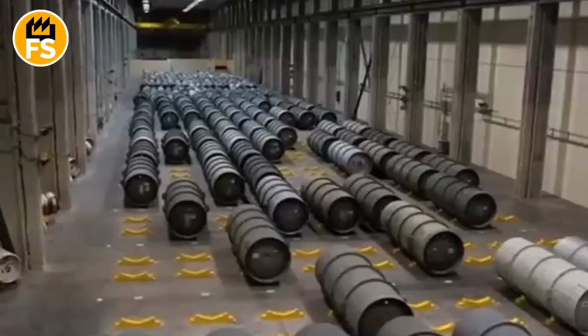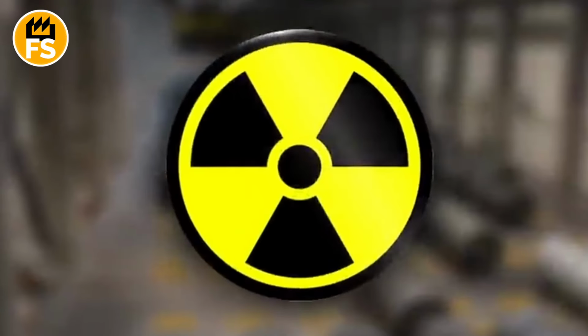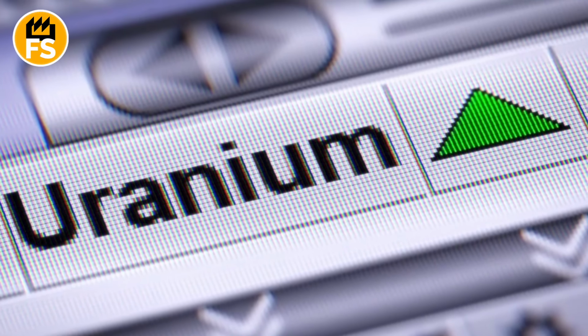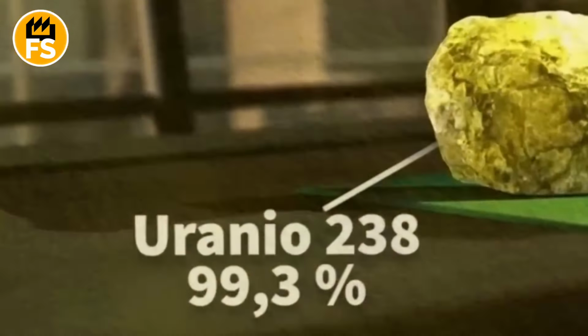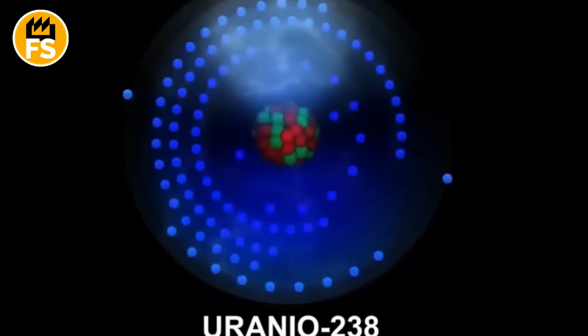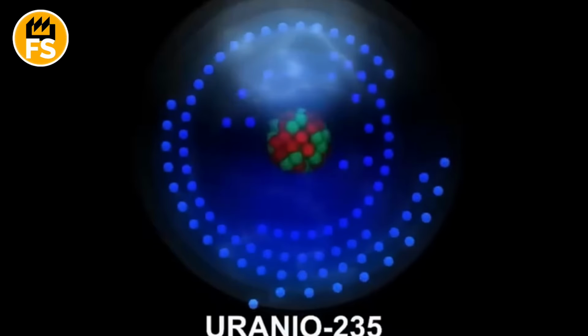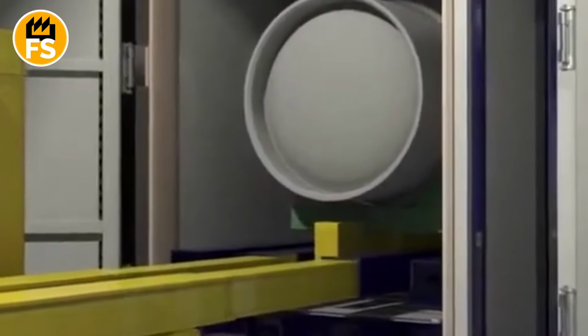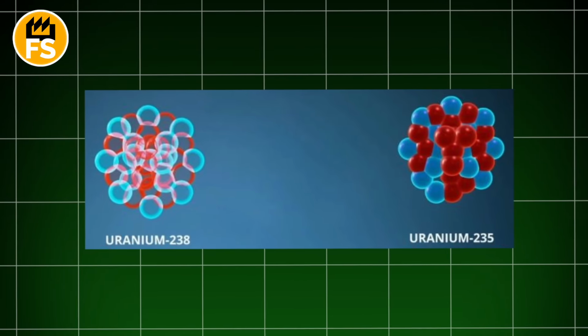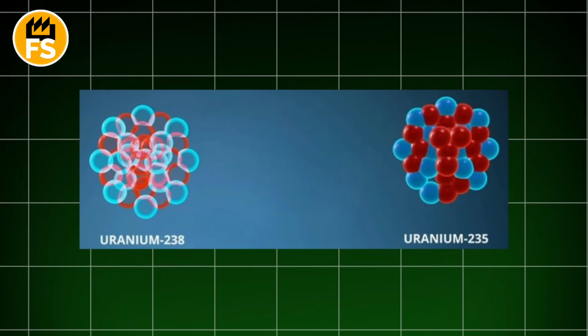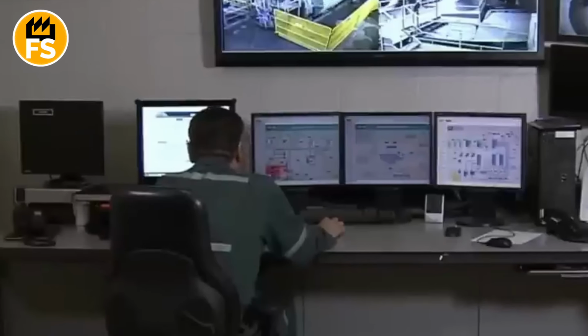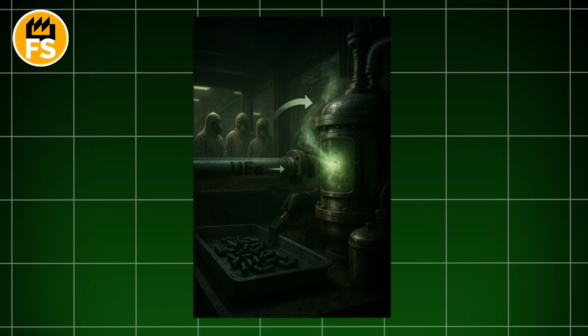But here the main problem arises, which is at the heart of all nuclear energy. In this perfectly pure uranium, 99.3% is the stable, lazy isotope uranium-238, which cannot sustain a chain reaction. And only 0.7% is the energetic, unstable isotope uranium-235, which is our fuel. They are chemical twins, and it is impossible to separate them by chemistry. To make the reactor work, we need to increase the concentration of this energetic uranium-235 from 0.7% to 3 or 5%. To begin enrichment, the solid uranium must be converted into a gas.